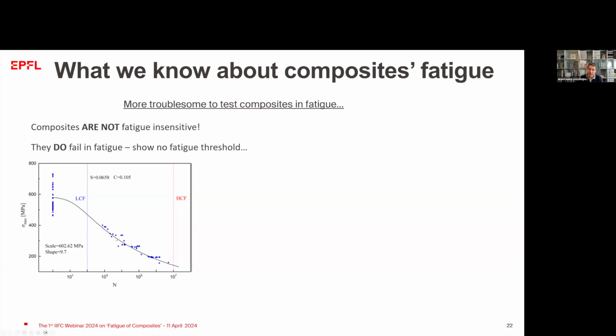And this scatter is related to the effects that I discussed before, the manufacturing defects that we might have, different material properties due to the manufacturing, due to the preconditioning of the materials, and so on. Actually, in composites, it is widely accepted as a rule that we accept as a valid test something that has at the same stress level more or less 1 decade of life difference. So here, if we go from 10 to the power of 4 to 10 to the power of 5, we see that the scatter at this stress level is this 1 decade of life. The same if we go lower or if we go higher. So this is more or less what is conceived as acceptable scatter in composites.